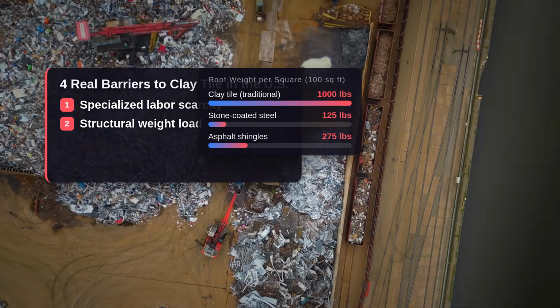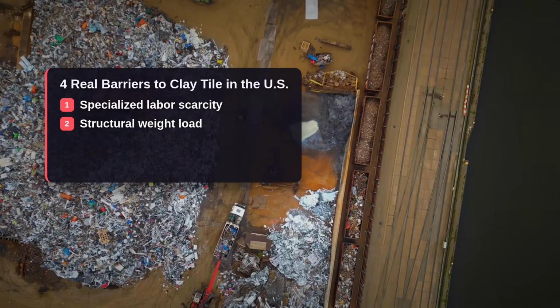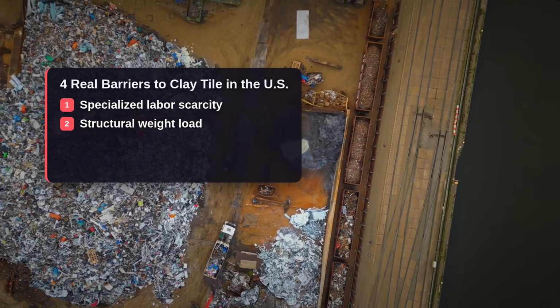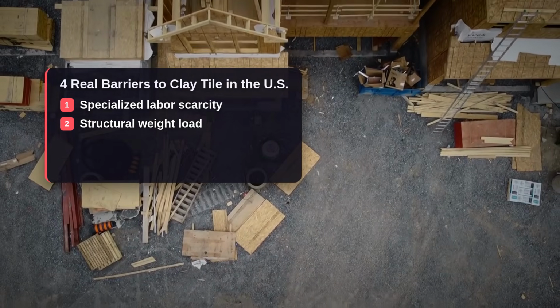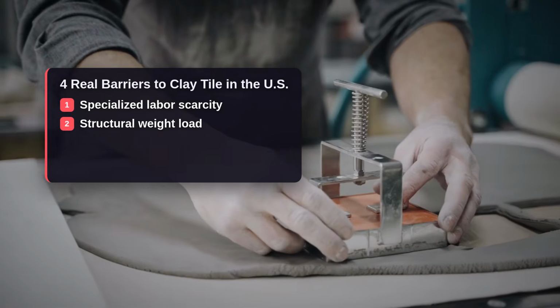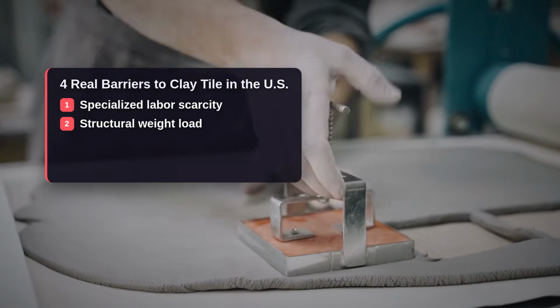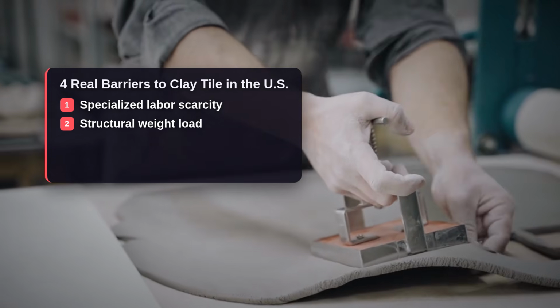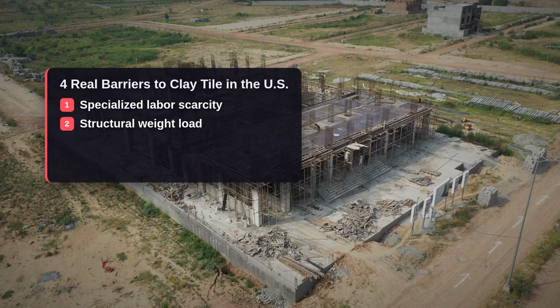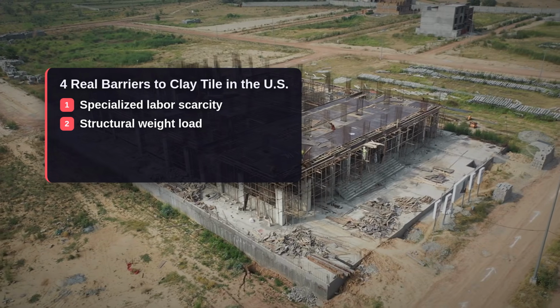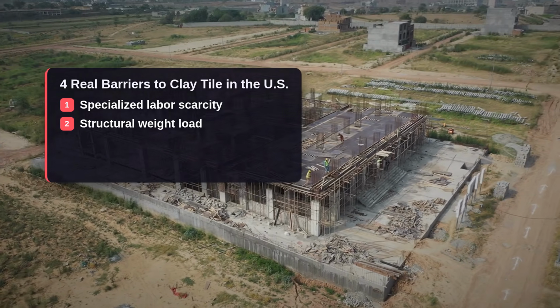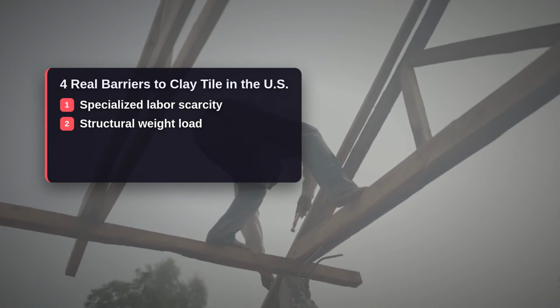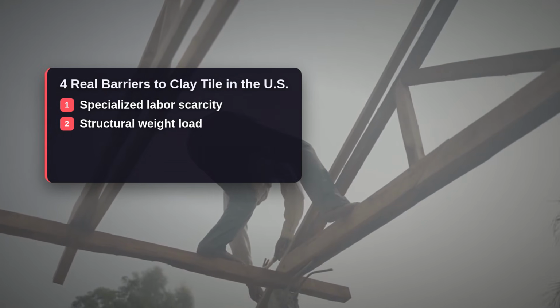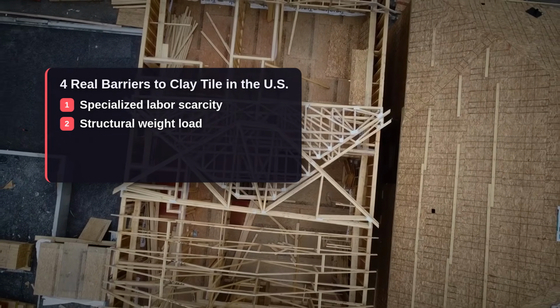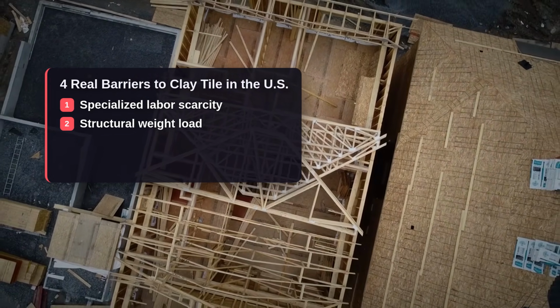The second barrier is structural. Traditional clay tile roofing weighs between 800 and 1,200 pounds per square, that is, per 100 square feet of roof area. A standard asphalt shingle assembly weighs 200 to 350 pounds per square. On a 2,000 square foot home with a moderately pitched roof, you might have 2,200 to 2,800 square feet of total roof surface. Switching from asphalt to traditional clay tile could add 15,000 to 25,000 pounds to the load on your roof framing system. Many homes built after 1960, using light frame lumber, were not engineered to carry that weight. Adding clay tile to an unmodified light frame roof can overstress rafters and ridge beams.